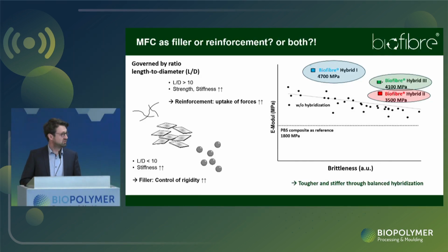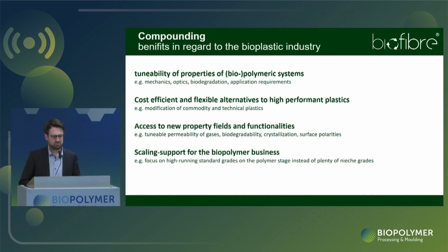And when you just use natural fibers in composites, you can have some certain enhancement of the E modulus, but still you have to cope with brittleness in the composites. But if you hybridize this, and if you fine-tune the different geometries, you can drastically enhance these ratios, and it gets tougher and stiffer through this balanced hybridization.